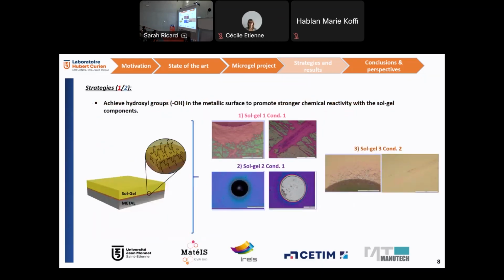The first strategy is to be able to activate the hydroxyl group on metallic surfaces. So with this hydroxyl group, you are able to create new bonding with the sol coating, covalent bond, in order to enhance this adhesion. When you are using this strategy in sol 1, condition 1, for example, it is not working. You can check here that the sol is delaminating in the Rockwell indentation, and for the scratch test it is a bad result too.